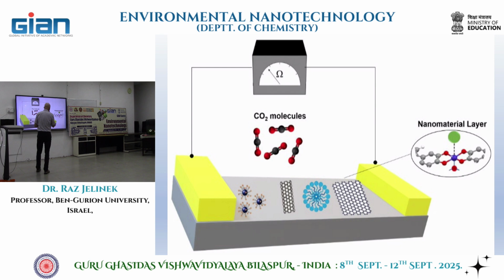For example, you can put a nanomaterial layer that will absorb very well carbon dioxide molecules. In this case, this is your target. If you absorb the carbon dioxide molecules to your medium, it will change the properties of this medium, and you're going to have a change of the resistance.